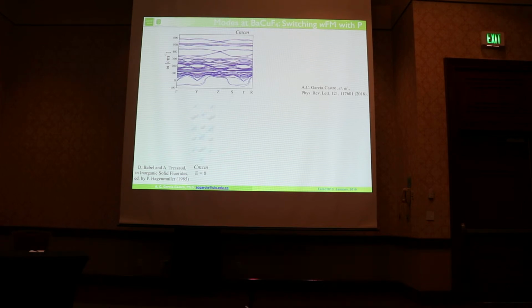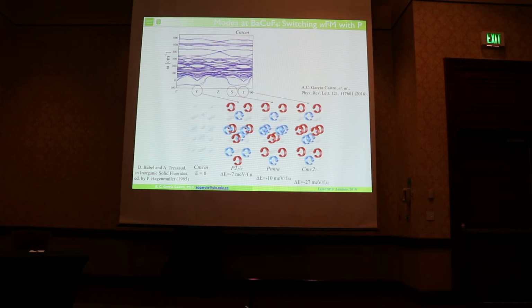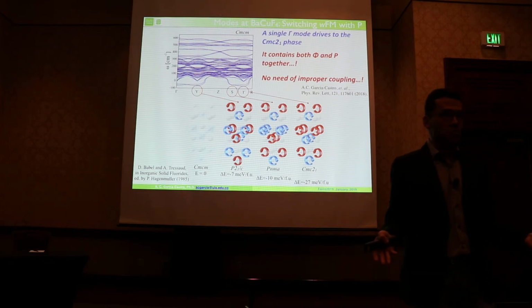Okay, so we wanted to go a little bit further in the analysis of this material, and we try to understand better the switching of the weak ferromagnetism through the polarization. And to do that, we computed the phonons at the supposed high temperature structure. I mean, it cannot be seen clearly, but what we observe here is that we have three different branches that are unstable at Y, S, and gamma. And these ones correspond to different rotation patterns, okay?